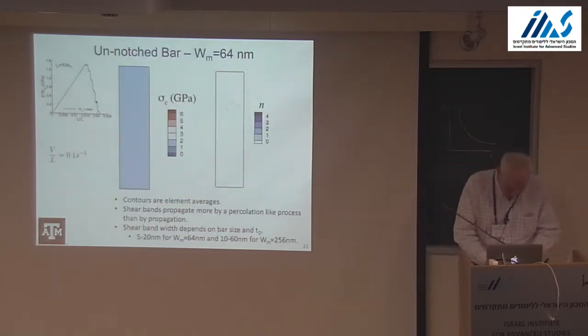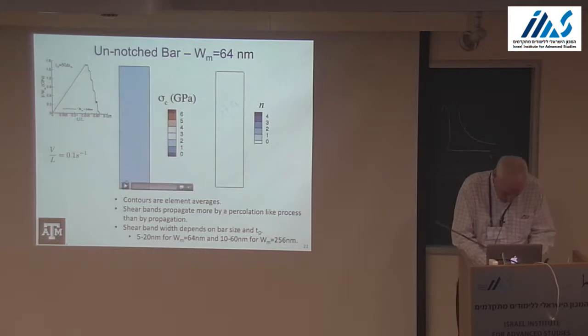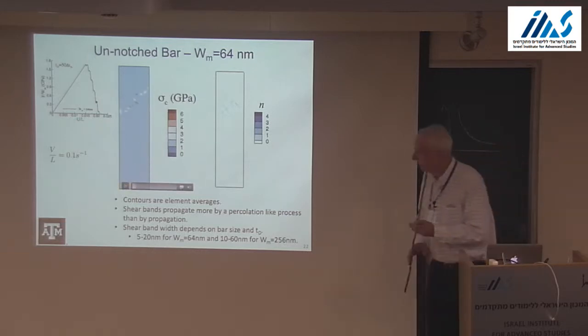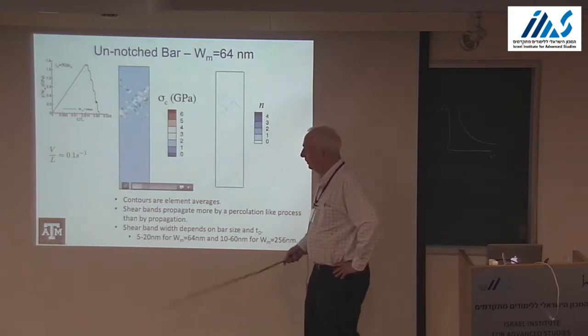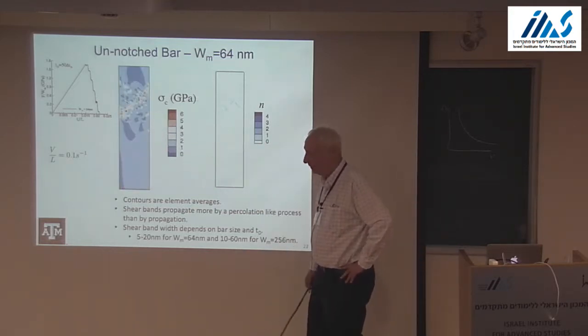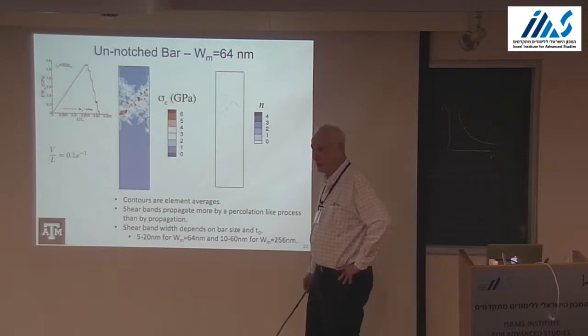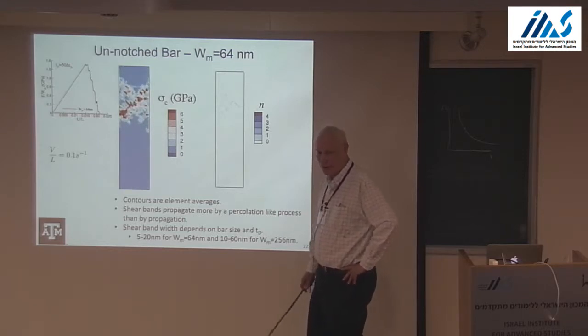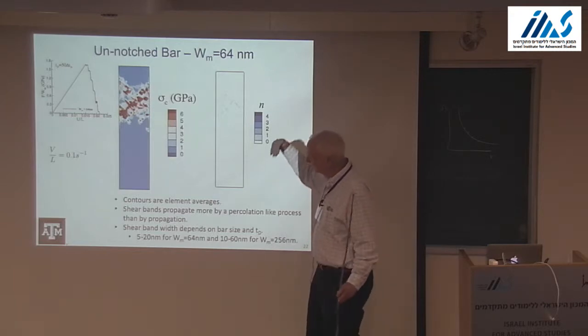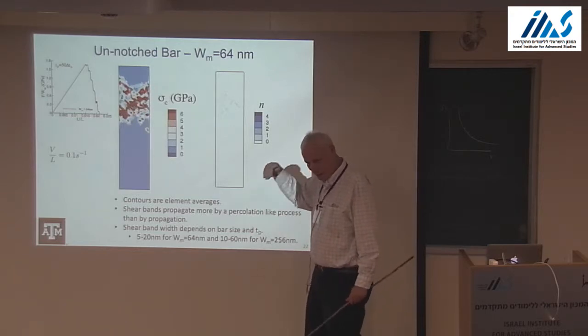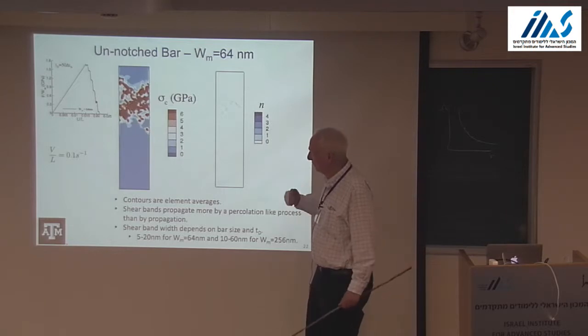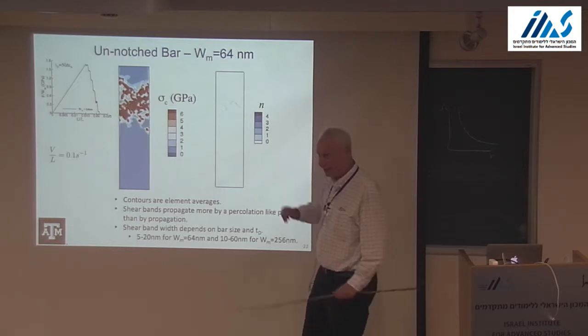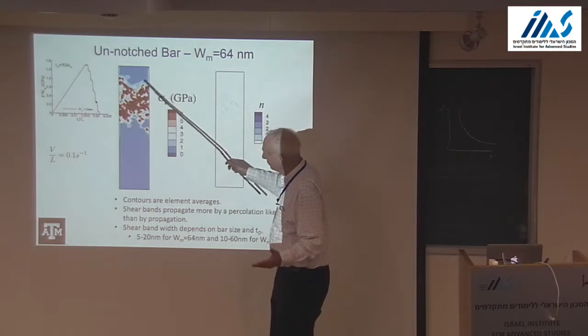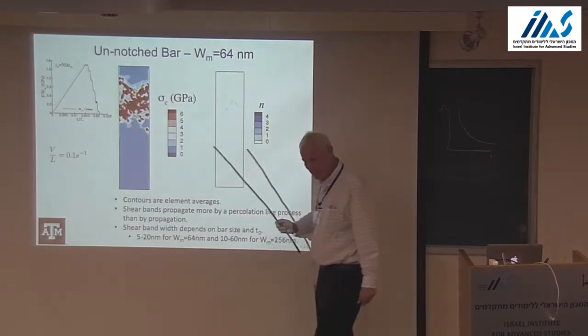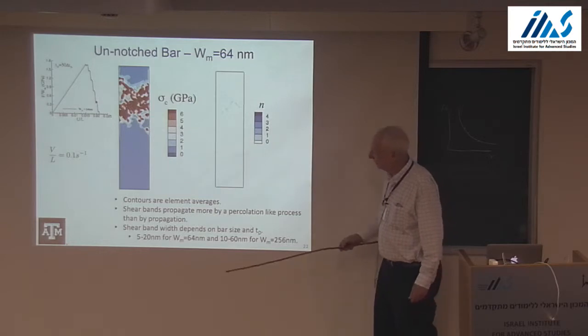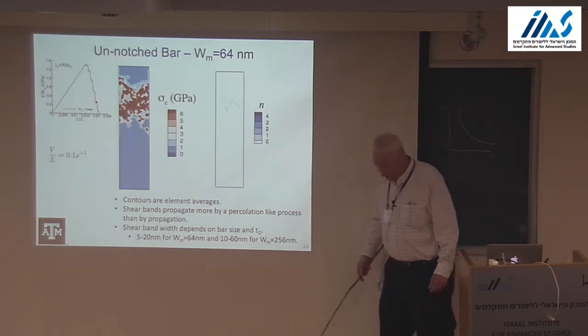I'll try to do one of these. What we see in the development of a shear band is that the shear band doesn't propagate. It really goes by a percolation type phenomenon, rather than something forming and propagating like a crack. Also, you can see as the shear band forms, you get some unloading around it, so that in this case, you get the shear band.